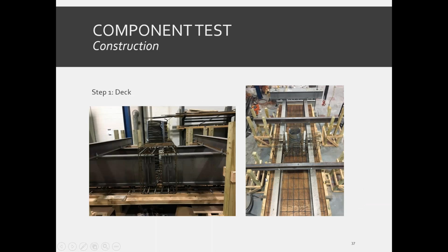Here are some photographs of the specimen before the casting of concrete. The specimen was sufficiently supported at the bottom to prevent any undue deflection. We used these auxiliary beams in the transverse direction to prevent movement of the girders during the concrete casting. We removed the beams later on. These auxiliary beams were used only because of the inverted test setup. This is, however, not needed on the site.